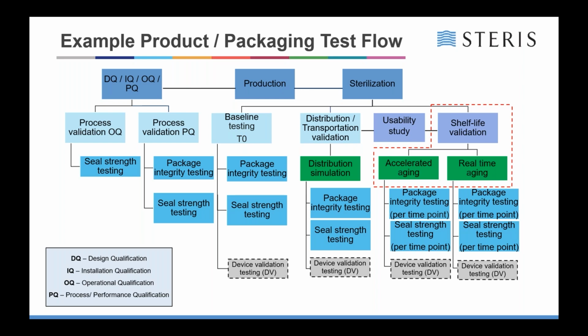And as you can see from the flow chart here, that goes all the way right across each of the processes, through the production, through sterilization. You then have the option to do either baseline testing or go directly into transportation testing. But the most important thing you have to do there is take the results, particularly from the seal strength testing, and be able to compare those back to your OQ settings and sealing parameters, because then you can show that the seal strength has not deviated significantly over the entire shelf life of the product.